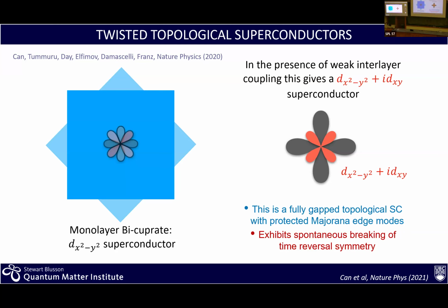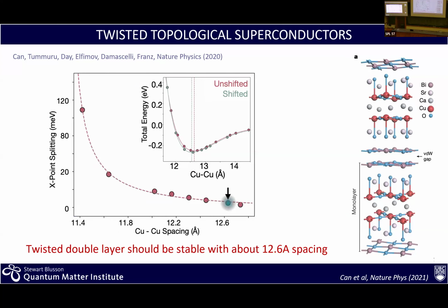So if you look at the full range in parameter space, there is an ideal range of interaction that you need. As a function of that parameter, which is a key parameter in the modeling, you have all kinds of phases. So the question really was for us, do we have a realistic and significant value for that parameter? So what we did was a calculation of it. We can use density functional theory. So that's where we go back and forth when you talk about material by design. Here is a concept. Can we make it? Now we can go in with a computational approach and see where we are. And then eventually the question is, can you actually fabricate this?